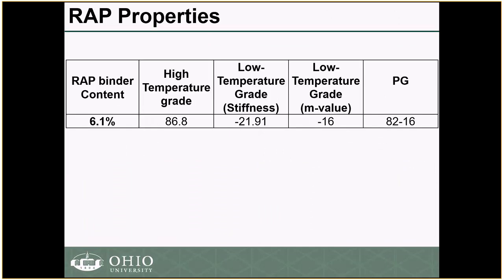Starting with the RAP, a very important thing is that the RAP used in this project was a little bit rich in terms of asphalt binder. It had about 6.1, which is higher than what is typically used. Typically it's about 5 to 5.25, the typical RAP binder content observed in the field, but this one was towards the higher end. I think that RAP was obtained from a job for Franklin County. The high temperature grade was 86.8, and the low temperature was minus 16.